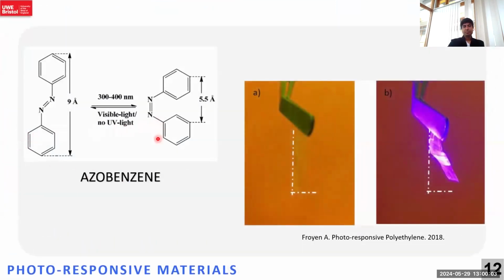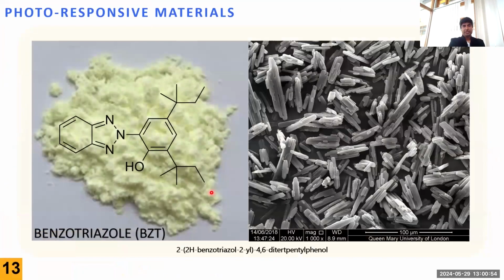the trans to cis transformation might not work well with the stiff polymers, although scientists believe that it is possible, and that the stiff polymer actuation is basically caused by the transformation of trans to cis state. But that would not be the case. And one of our research group was working on this state and found that this is not only because of the isomerization of the azobenzene, but also because of the photothermal generation of heat when the trans state is being converted into cis state. So moving forward to that, we believe that benzotriazole BZT is an ideal material to be used as a photoresponsive agent within polyethylene.